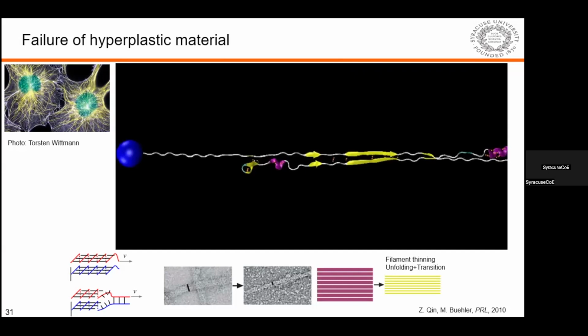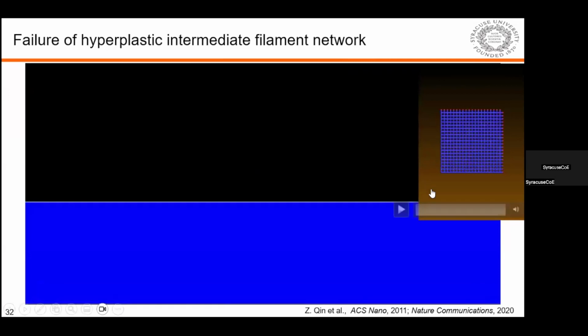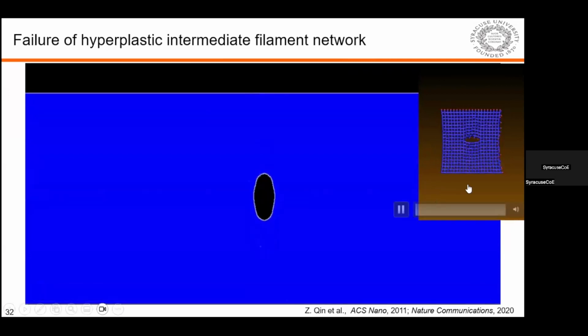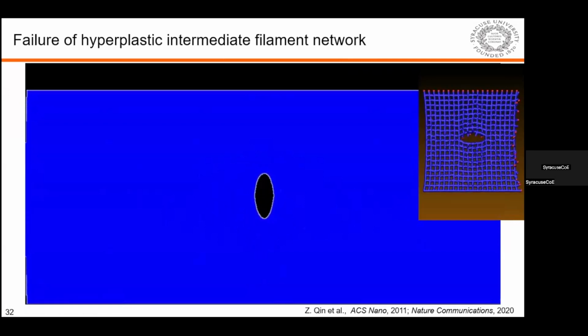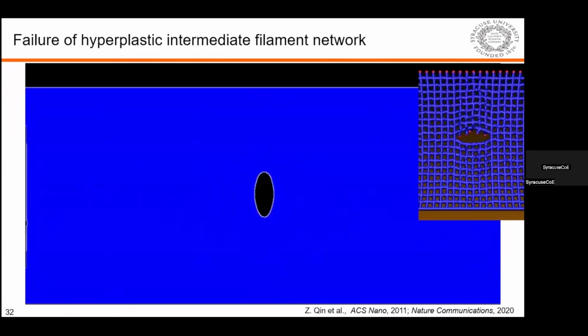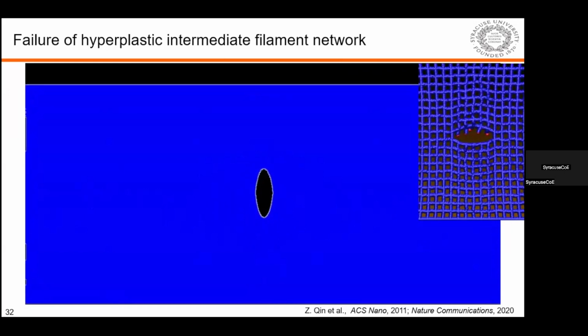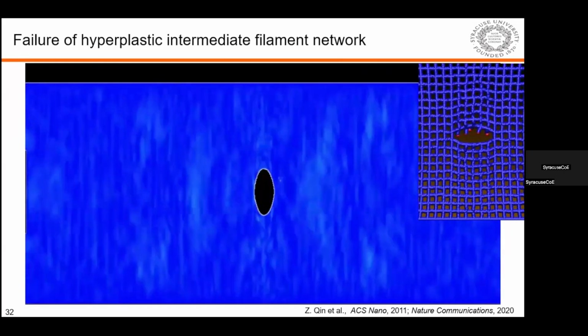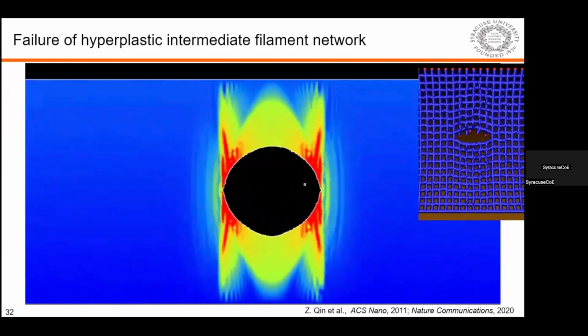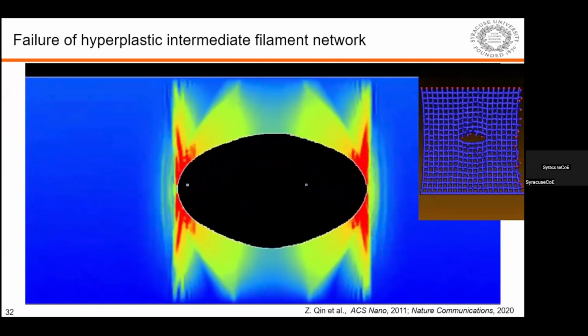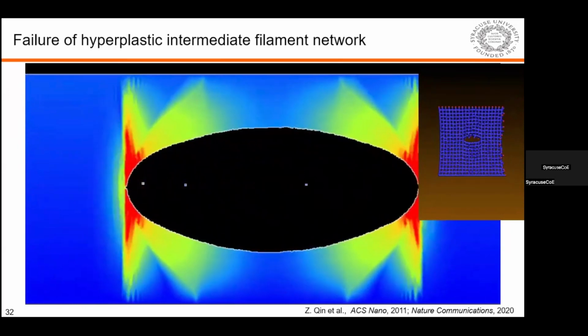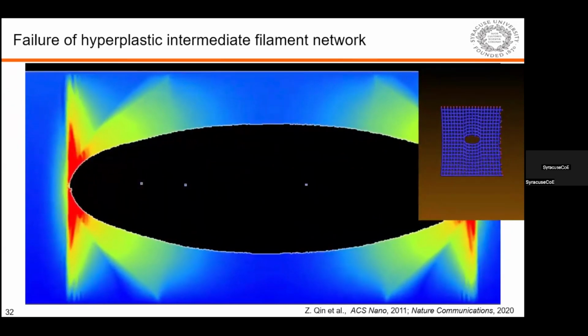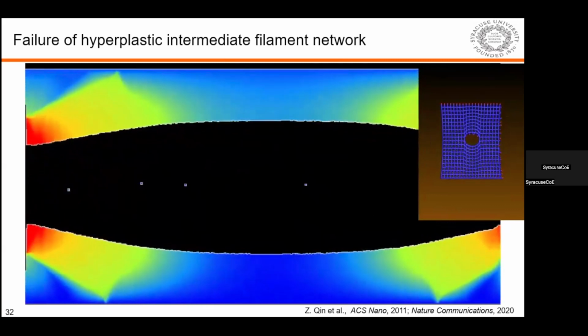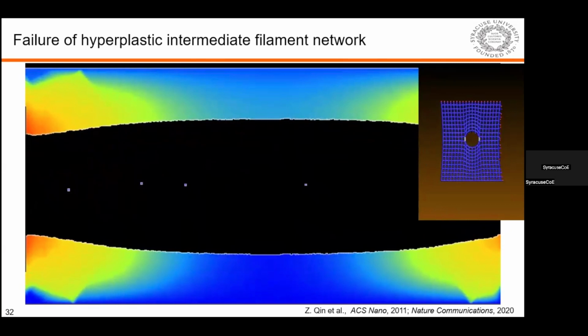Based on these atomistic simulations, we built a coarse-grained model to visualize that once you have a small network and apply loading to these intermediate filaments, because of the hyperelasticity and stiffening behavior of the fiber, they will not crack immediately. Instead, the shape of the crack changes significantly from a single line to an ellipse. That reduces the stress concentration, and that makes this network much more difficult to fail.